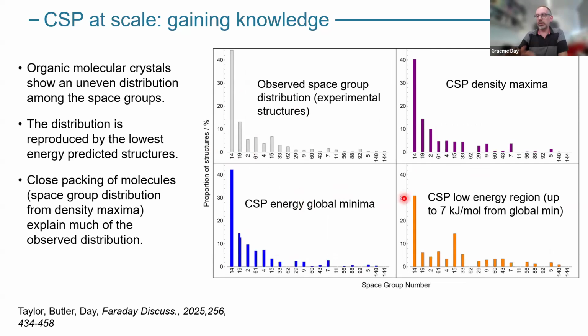We can then look at what happens if you start to include structures that are higher up the landscape. And now you start to see those distributions start to level out a bit. So you can understand then these space group distributions or biases in observed structures. It is energy driven, okay? Because if you start to go up to higher energies, then you start to see those biases start to level out.